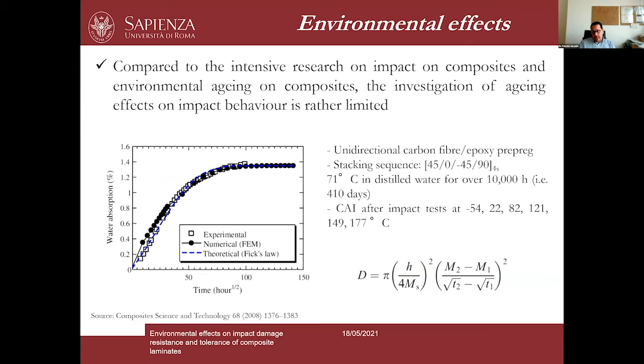And if it is true that there are a lot of studies dealing with the effects of a low velocity impact on composite materials, or studies dealing with the environmental aging on composite materials, instead, the need to correlate the aging effects with the impact resistance of a composite material has received a limited attention in literature. Despite there are some studies, and here, for example, you can see the typical water absorption curve of a standard conventional composite material based on carbon fibers embedded in an epoxy matrix.